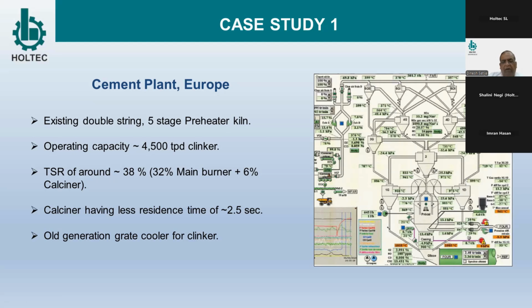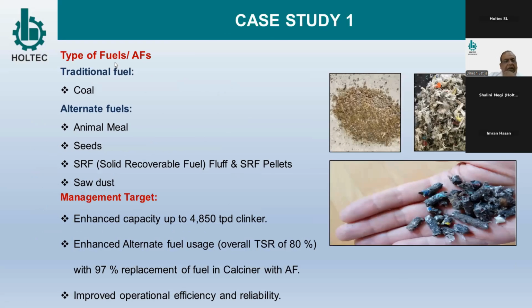So this is a plant in Europe, and these were the main fuels. The main traditional fuel was of course coal, and the alternates were animal meal, seeds, solid recovered fuel, fluff, and sawdust. The management target was to enhance the capacity marginally from 4,500 to 4,850. But the major thrust was to enhance alternate fuel. Overall, the TSR target was 80%, with 97% replacement in calciner fuel. So we were supposed to replace the complete fuel in the calciner with alternate fuel. Of course, overall operational efficiency improvement and reliability improvement.